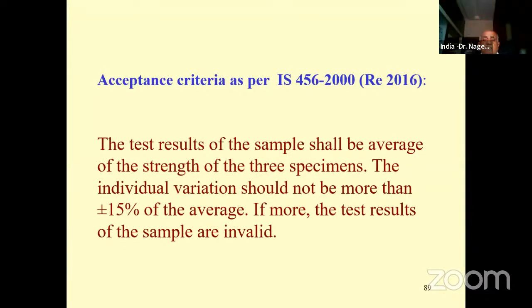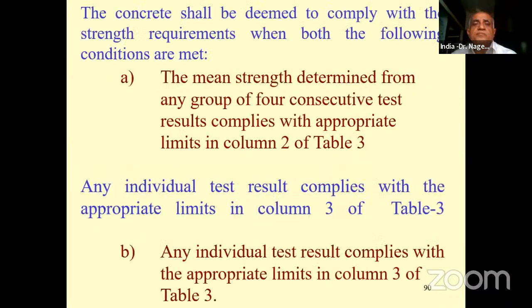Now, coming to acceptance criteria. What is the acceptance criteria? Plus or minus 15% of the average. If more, the tests of the samples are invalid. So when you take the results of 3 cubes, find out the average and apply 0.85 times the average value, that should be the minimum value, and 1.15 times the average value, that is plus 15%, is the maximum value that can occur.